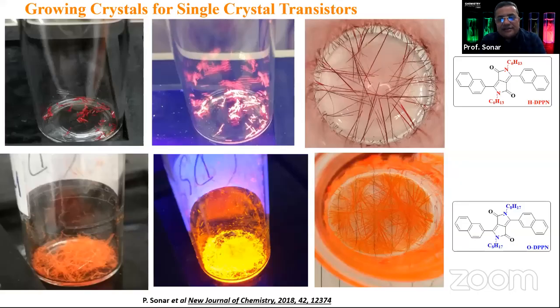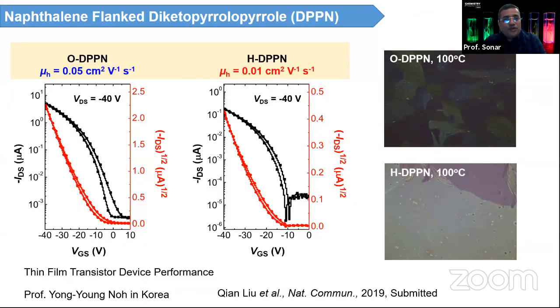The important thing here is this dye, which we can grow as a single crystal, and single crystal transistor is another interesting aspect. And you can see nice colors and crystals, needle-like. We put up those needles. I mean, we first made the thin film and measured the transistor mobility, and we got these values 0.05 and 0.01. The mobility values of these materials are rather low compared to the earlier values which I showed, which were very high. But don't forget that this is just a small monomer, a small molecule. It is not a polymer. And still for a monomer, this value is very high.